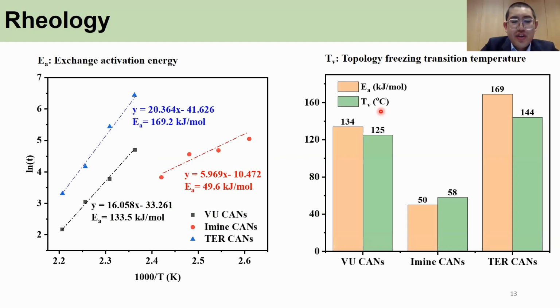The rheology of the material is used to describe the dynamic exchange process at high temperatures. We found the imine CANs have the lowest activation energy and the Tv, which is because of the modified lignin with the aldehyde group we made had the lowest modification degree. To improve this, we add some commercial dialdehyde to the system.